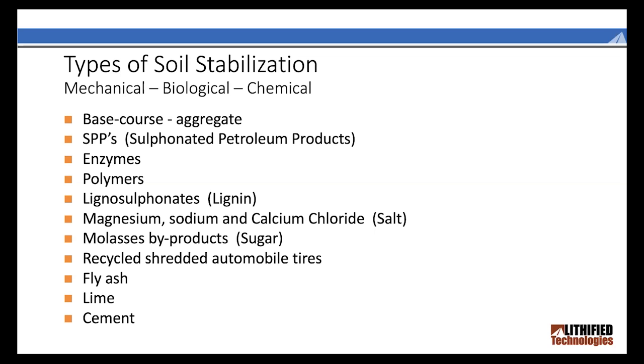Now, the downside with lime is it will stiffen the soil, and it typically will not get over 160 PSI unconfined compressive strength. And Lhoist is the largest lime producer in the world, and that's their target, is just to achieve 160 psi unconfined compressive strength, and then put some kind of surface over it as fast as you can to try to keep the water out.